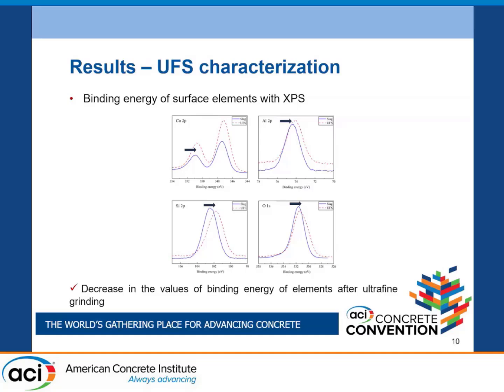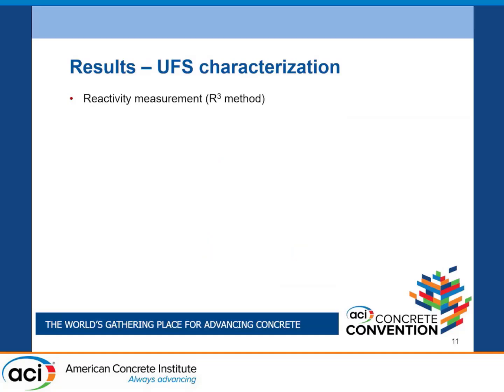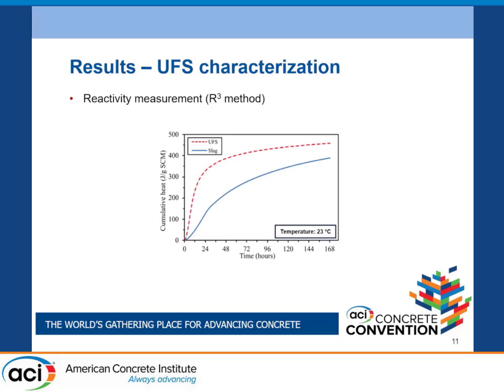And also, for the calcium peak, we saw a huge increase in the intensity of the calcium peak in the UFS compared to the slag, which means that more calcium is now available on the surface of the UFS, so it can contribute to the reactions again faster and to a higher degree. We did the reactivity measurements on the slag and UFS, and our UFS after grinding has a higher reactivity compared to the slag. We did the test at 23 degrees.